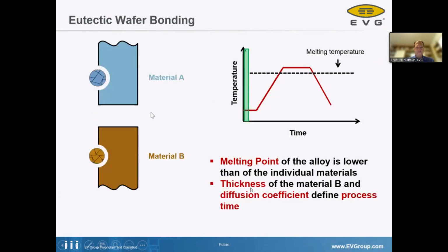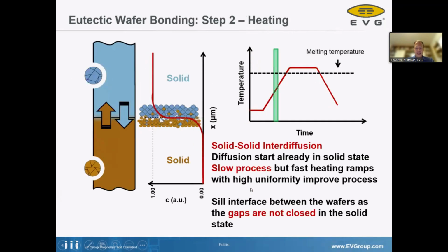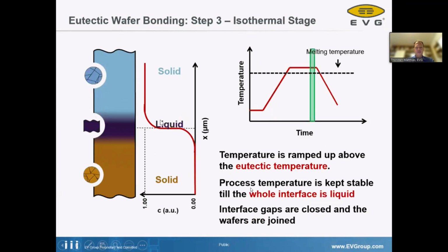liquidus point. And so what happens is, at some point in time when I have had enough of this metal ion diffusion, and here we see the temperature curve in the bonder, then my entire system is at a temperature higher than my eutectic point. Then I start to see some liquid interface, and all my voids and gaps between my seal rings are being closed just by the properties of having a liquid in the interface. And then I have to cool down.